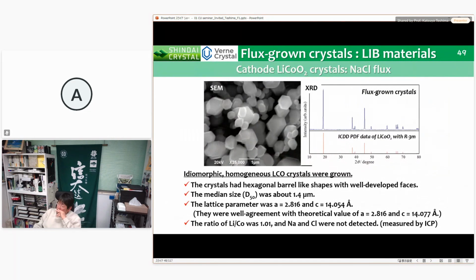These are the LCO crystals grown from NaCl flux. Idiomorphic, homogeneous LCO crystals were grown by the NaCl flux. The crystals have hexagonal barrel-like shapes with well-developed facets. The median size was about 1.4 micrometer.